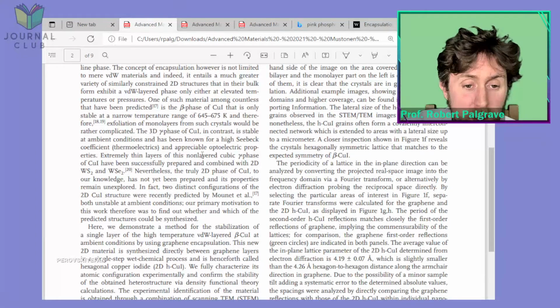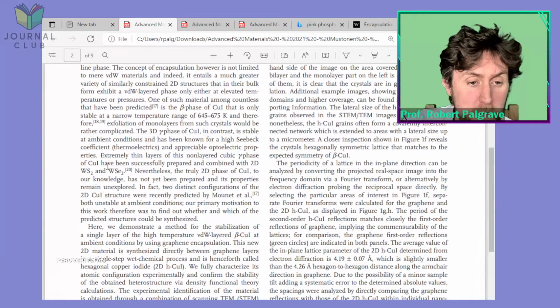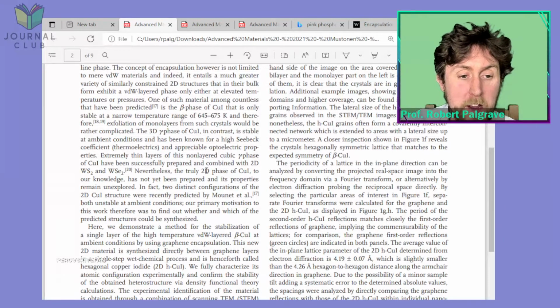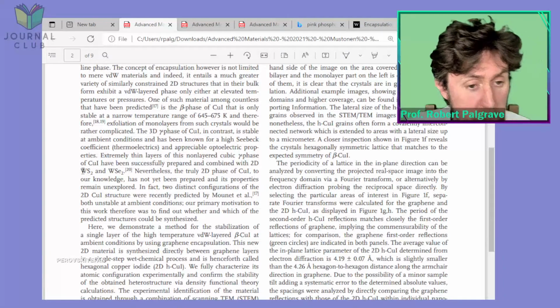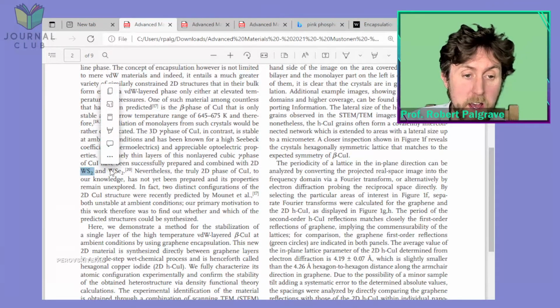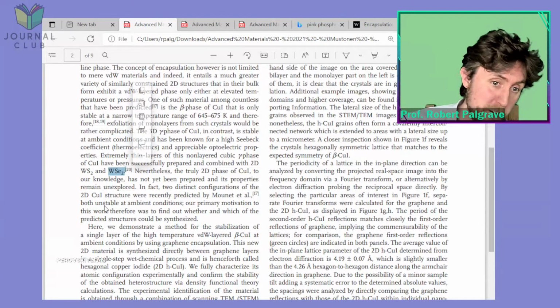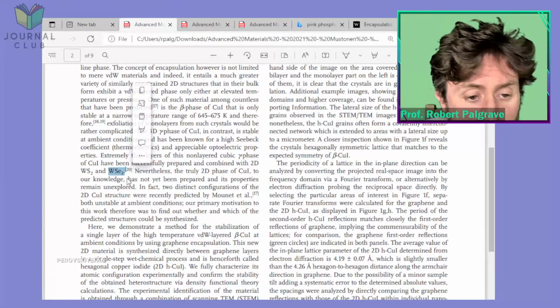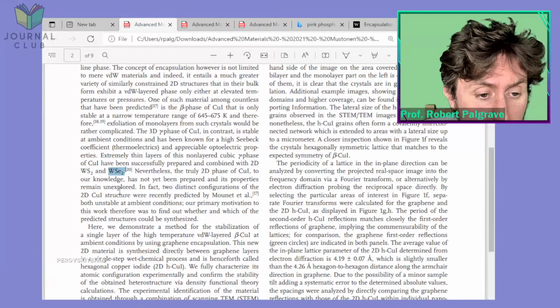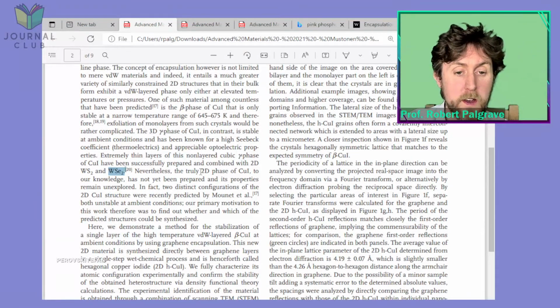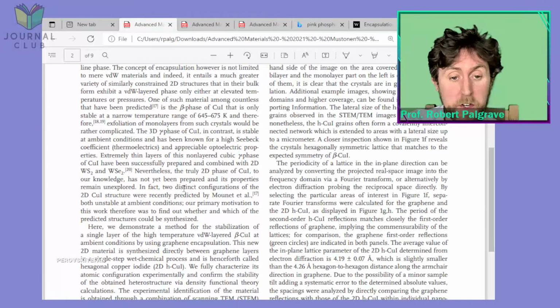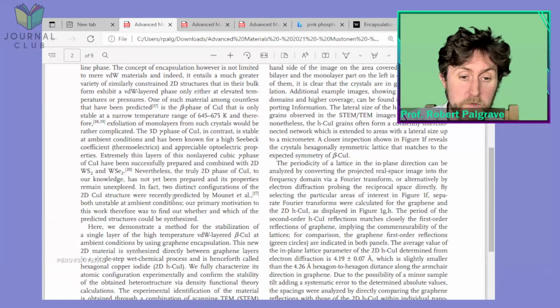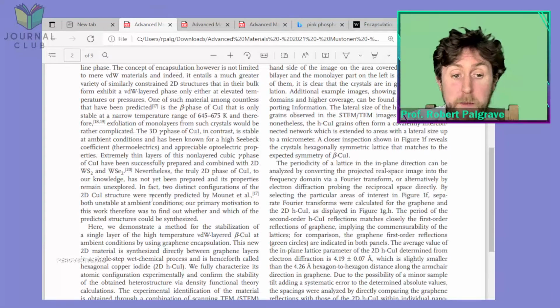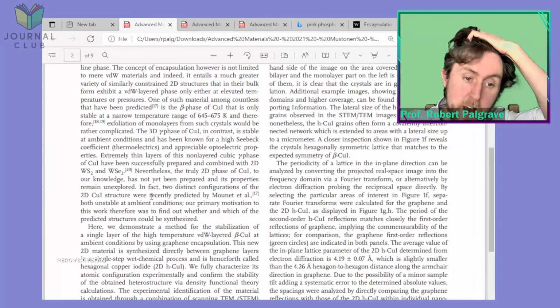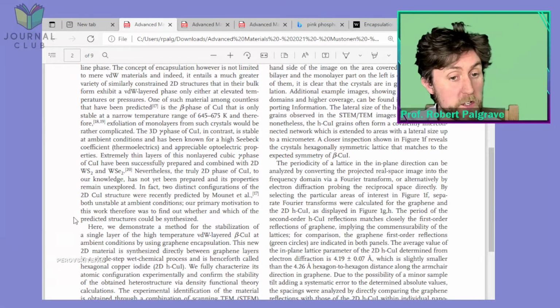Extremely thin layers of this non-layered cubic gamma phase of cuprous iodide have been successfully prepared and combined with 2D tungsten disulfide, one of these transition metal dichalcogenides, and tungsten selenide, another one of the transition metal dichalcogenides. Nevertheless, the truly 2D phase of cuprous iodide, to our knowledge, has not been prepared, and its properties remain unexplored. In fact, 2 distinct configurations of the 2D cuprous iodide structure were recently predicted by these guys. I'm guessing in a theory paper. I haven't read that paper. Both are unstable at ambient conditions, and our primary motivation in this work therefore was to find out whether and which of the predicted structures could be synthesized.